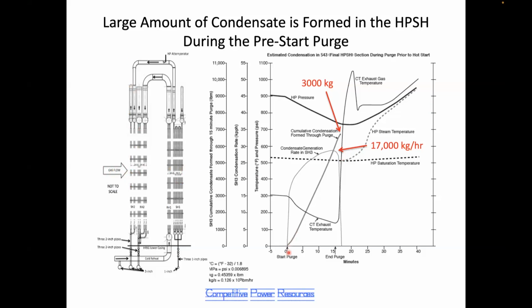This little curve over here is the calculated value of the rate of condensation that occurs in just this one row of tubes right here. And that rate of condensation peaks at 17,000 kilograms per hour. Over the 15-minute period that the purge is occurring, 3,000 kilograms of water is accumulated just in this one tube section right here. That's enough water in this configuration, if it's not removed, to flood up into the tubes. So that's the key difficulty during startup, particularly hot startup with the horizontal gas path HRSG: all this water that condenses and accumulates in the superheater.